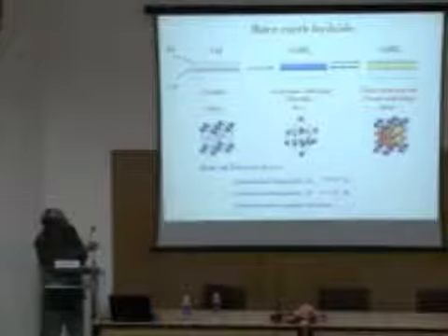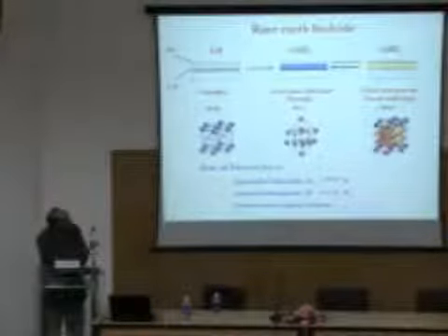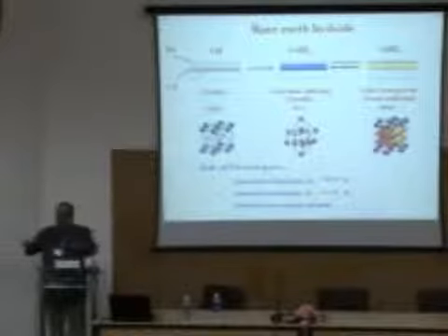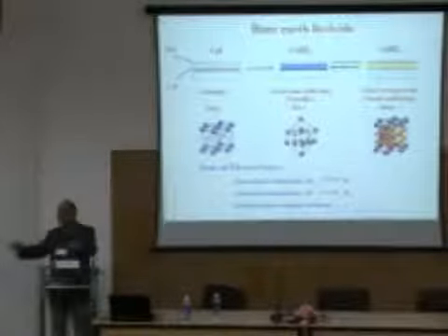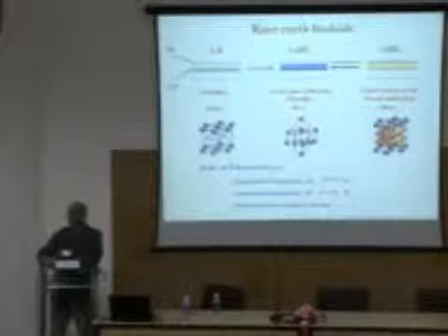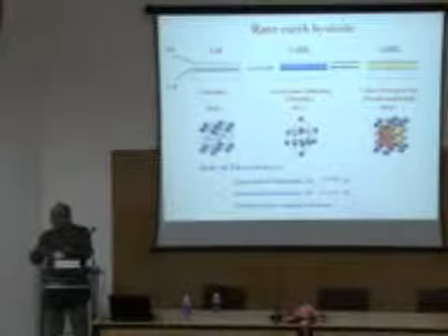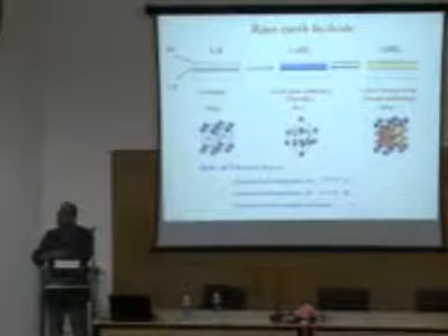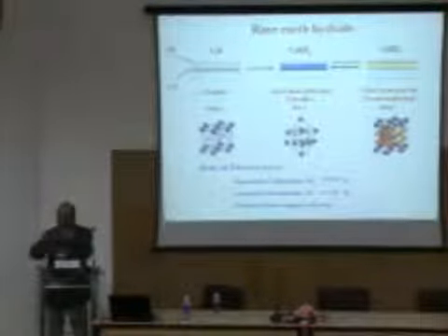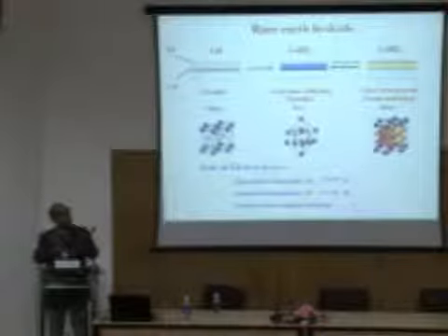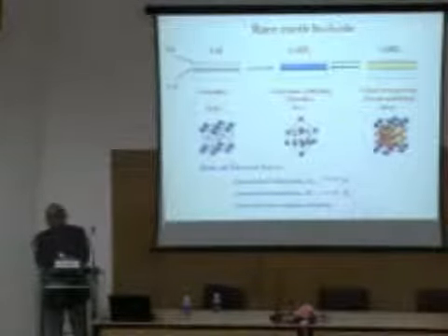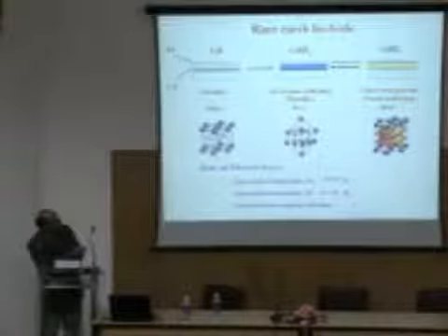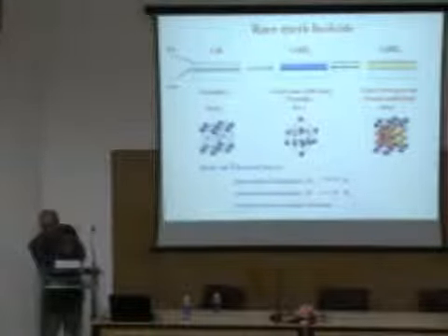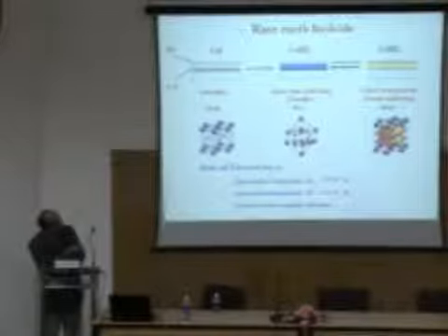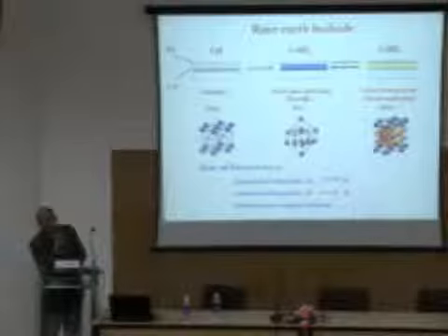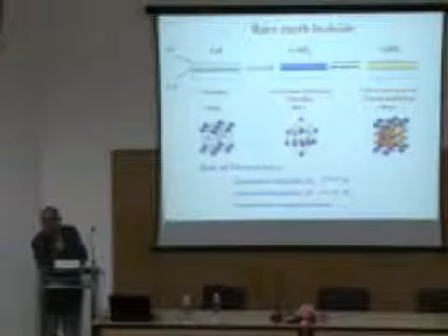During this process, from dihydride to trihydride, when the hydrogen is coming back, again, two atoms of hydrogen must come together at a palladium site. It is not that they can just come together anywhere and a molecule of hydrogen can be formed. It does not happen. The catalytic reaction has to take place. Two atoms of hydrogen have to come together at a palladium site, and then a molecule of hydrogen is formed, and what comes out is a molecule of hydrogen. So palladium plays an important role during what is called dissociative adsorption when the hydrogen is going in, and associative desorption when hydrogen is coming out, during loading or during deloading.